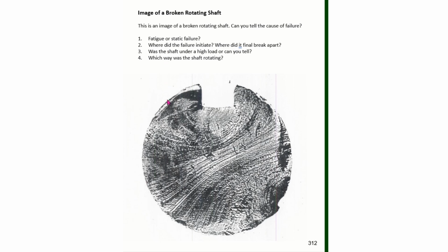Where did the failure initiate? Well, we know that cracks need to be under tension to propagate. And so the crack to propagate needed to be under a tension load, opening the crack up. And right here in this keyway, we can see localized lines propagating in an outward direction, and those lines continue on, like shown here, until finally we come down to this part and have a brittle fracture.